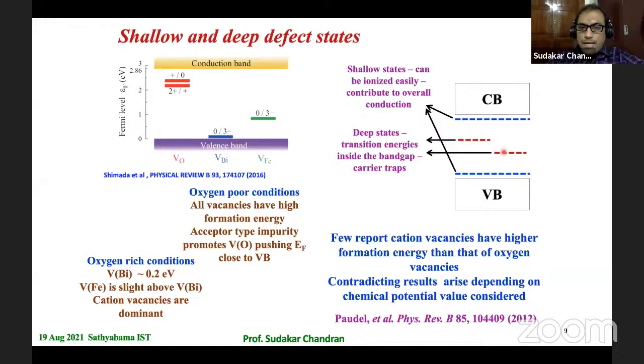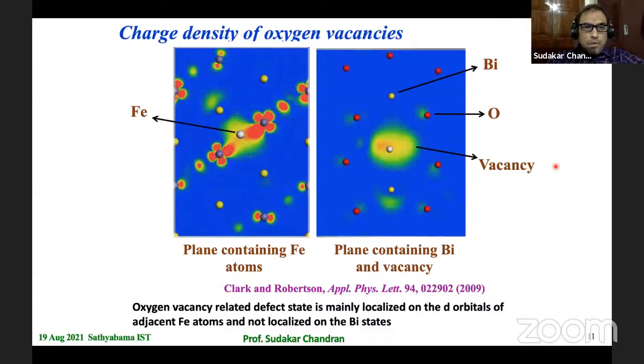Of course, those states which lie deep might affect the properties as well by trapping the charge carriers, but we may not come across that in our case much. But whenever the oxygen vacancies do exist in this particular structure, it can be seen that the oxygen vacancy related defect states are mainly localized close to the iron sites rather than the bismuth sites. So these are the charge density distributions due to the oxygen vacancies, shown from this particular paper by Clark and Robertson, which clearly demonstrates where the vacancy related energy levels reside, and therefore how they can influence the properties.